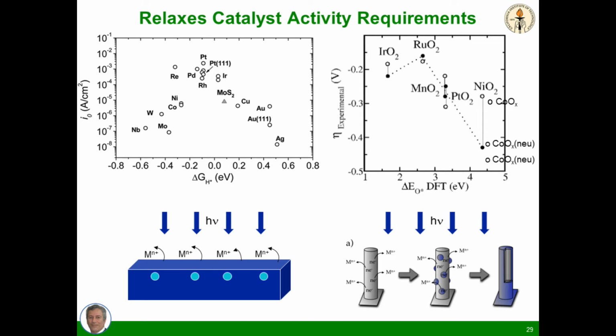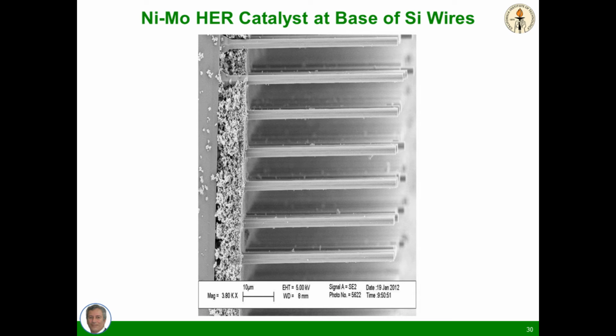To demonstrate this, the next slide shows that we have placed nickel molybdenum, which is not as active as platinum on a per site basis, in sufficient mass loading, but at the base of the microwire arrays, where instead of blocking light, they reflect light back into the structure, along with the titanium dioxide scattering layer to serve as an optical scattering and light management system. And we've shown that by using this three-dimensional architecture, we can obviate the need for noble metal catalysts for the hydrogen evolution reaction and instead use non-precious metal catalysts for the same effect and same efficiency in these systems.